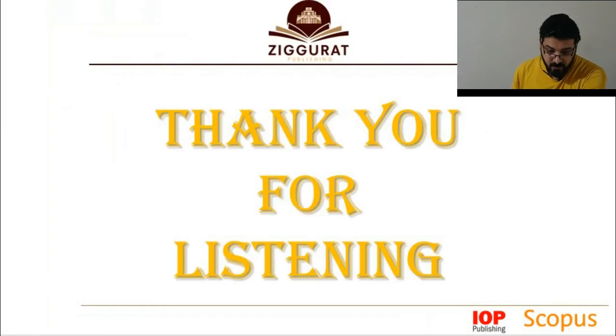The conclusion, the first one: the addition of graphene to the LCNO reduces mass loss because its sheets act as filler reinforcing particles which attract the mixture compound. Second, there is a critical adding percent of graphene at 6% that leads to increasing mass loss at high temperature, which occurs due to the reinforcing effect of graphene reducing the mixture components' segmental mobility. And last, it was found that the suitable graphene addition is 4%, which has high thermal stability and low mass loss, and the annealing temperature of 750 centigrade. Thank you so much for listening.